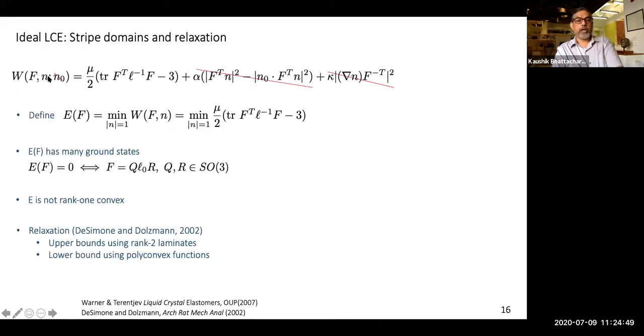So if I were to go back here and ask what is the effective behavior, one of the really remarkable results in this field is that Antonio DeSimone and Georg Dolzmann were able to actually compute exactly the relaxed energy. This is one of the very few examples where you can explicitly compute the entire free energy relaxation. And this was done by the usual technique of finding upper bounds by doing particular constructions and then using some theory to obtain a lower bound.